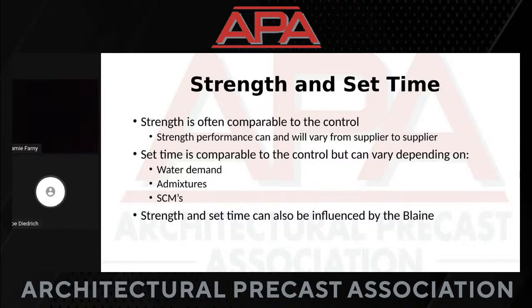With architectural concrete, my advice when trying a Portland limestone cement is, if you see the water increase, you might consider bumping up your admixture to compensate for that additional water demand. That will help you maintain color. And then last but not least, strength and set time. These are all influenced by the Blaine. Next slide.